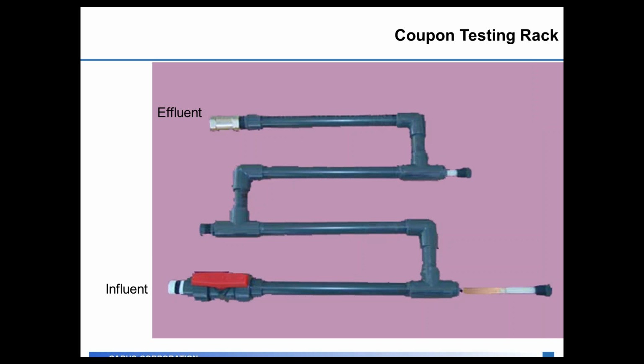Specifically, here's a picture of a coupon rack. The typical rack that you would see in the distribution system would be a 3-position rack, and you would have copper, lead, and mild steel coupons that you would put out there in the distribution system. The rack is controlled with the silver dole valve that impacts how much water would flow through the rack. Typically, you're going to control it at 1 gallon per minute or 2 gallons per minute going through the coupon rack in the distribution system. And like I said earlier, you'd have 2 of these, one on treated and one on non-treated water.